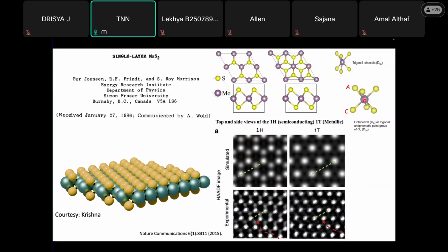But in the 1T phase, since the sulfurs are not in the same column, the sulfur column will not be visible. So only the three things corresponding to the molybdenum sites are visible. In this way, you can easily look in the transmission electron microscope, particularly scanning transmission electron microscope in dark field imaging. You can see whether this is a 2H phase or 1H phase or 1T phase.